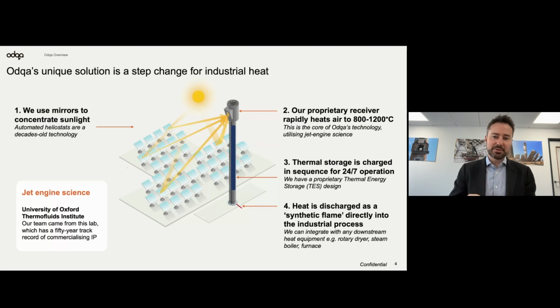It's an air-based receiver that can rapidly heat air up to 800 degrees, which is what we have proven at scale in the field, and up to 1,200 degrees, which is proven in our lab here in Oxford. Talking of Oxford, the reason that we've been able to create this breakthrough technology, this proprietary receiver technology, is because